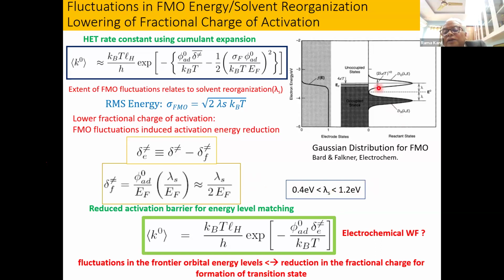So effectively, we are picturing a Gaussian distribution of my FMO orbital energies also. So effectively, we get a kind of reduced activation barrier, because the fractional charge required to match that energy is reducing. So solvent reorganization acts as a facilitator in electron transfer kinetics.